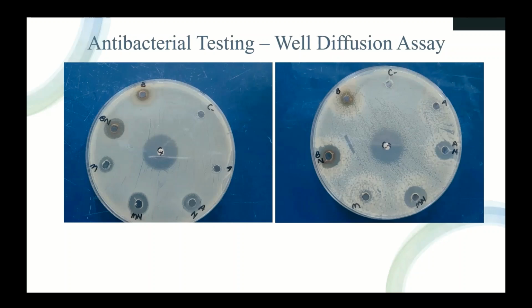On the right-hand side, we see a similar structure with the other bacterium that we used. And again, acacia honey had no activity, but the acacia honey nanoparticle was about 50% that of the positive control, indicating that when the acacia honey was used to cap and reduce the nanoparticles, it worked better than the manuka honey nanoparticle or the buckwheat nanoparticle. Next slide, please.